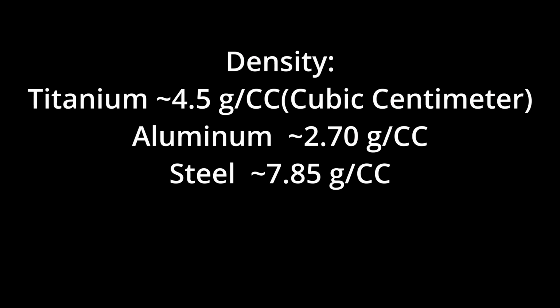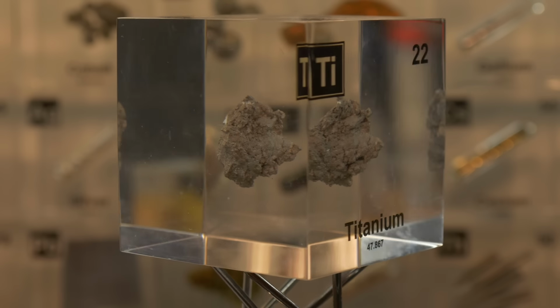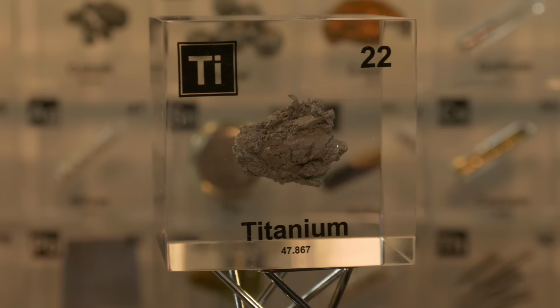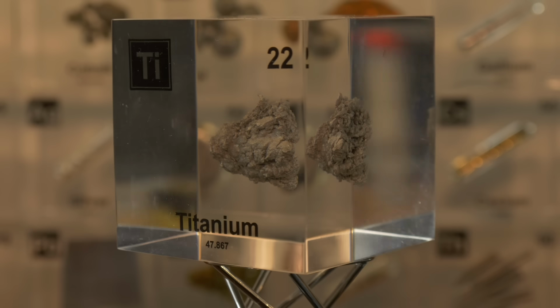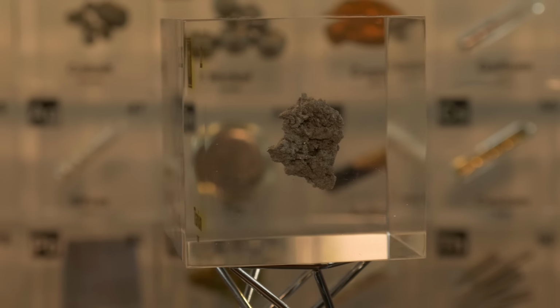Titanium's density, about 4.5 grams per cubic centimeter, is roughly midway between aluminum, lighter, and steel, heavier. It's denser than aluminum, which is why titanium items are not quite as feather-light as aluminum ones, but much less dense than steel. This means titanium strikes a sweet spot, not too heavy, not too soft. Now, in practical terms, a solid titanium object is 60% heavier than the same size aluminum object, but will also be much stronger. It's this balance that makes titanium ideal for applications where both strength and low weight are critical.